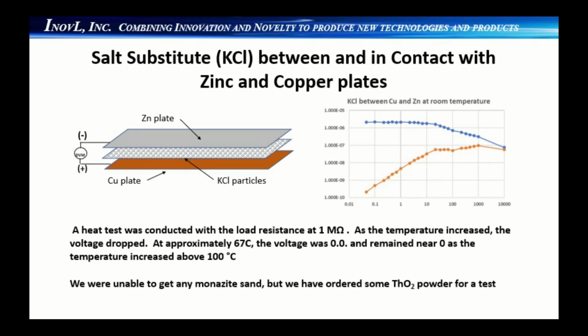We let the cell cool overnight, and by the next morning the voltage was back to the initial room temperature values, possibly indicating that the salt substitute had absorbed enough moisture to become an electrolyte. These results reinforce the need to conduct experiments to differentiate results from oxidation reduction reactions and results produced by ionized gas.